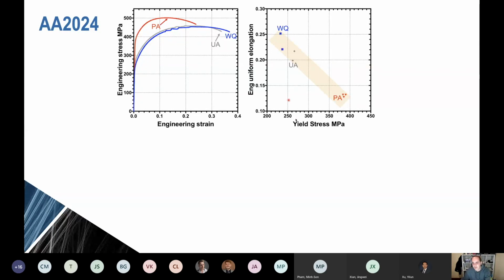If we plot the yield strength and the uniform elongation from these 3 curves, we have this completely normal inverse correlation that we typically see in engineering alloys. So here's the peak age state, the water quenched and the underaged. And the multiple points just correspond to multiple tests so you can see the reproducibility.